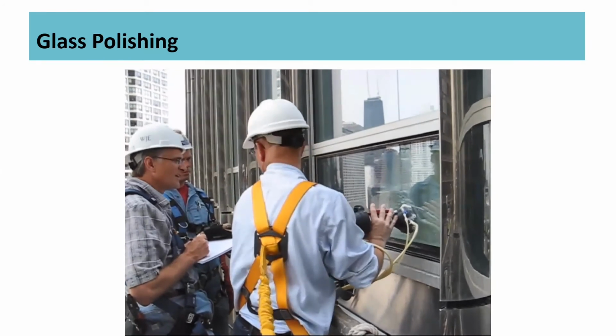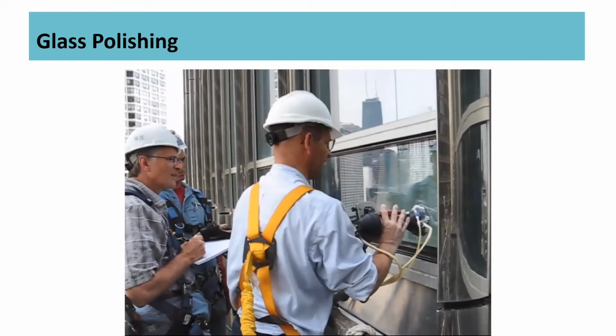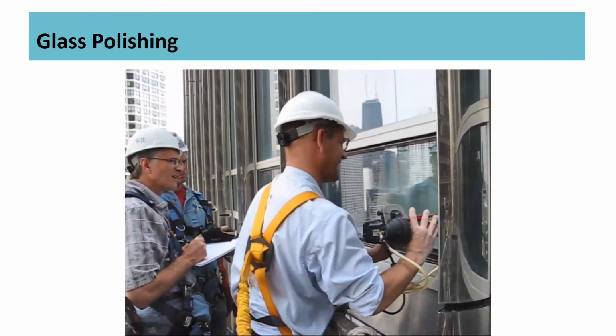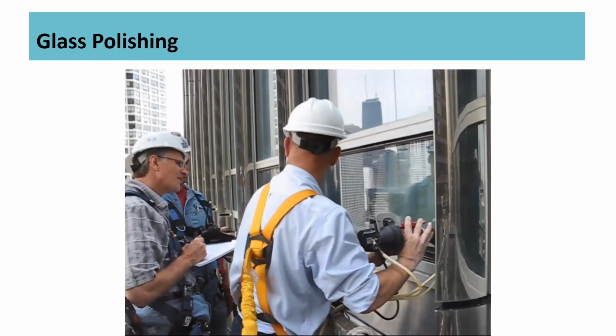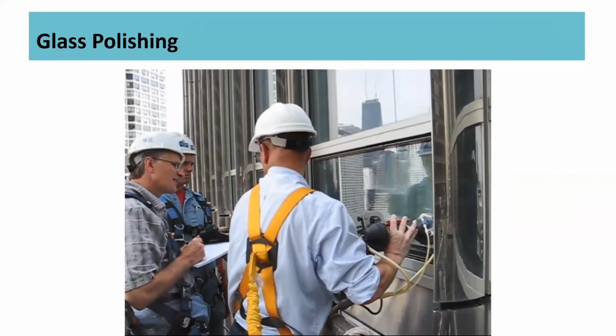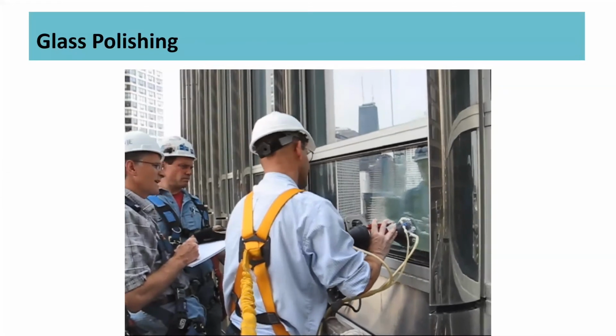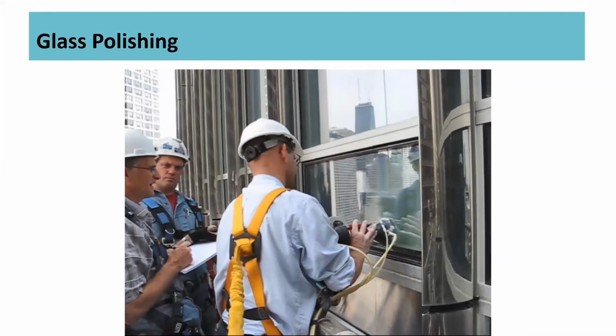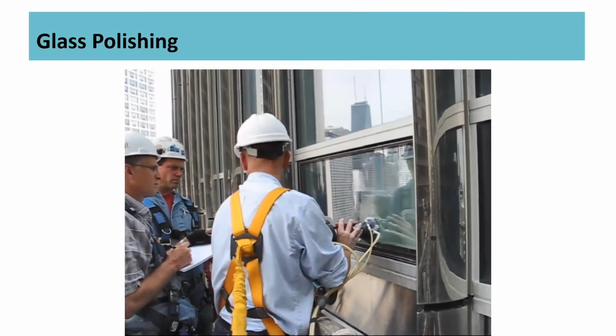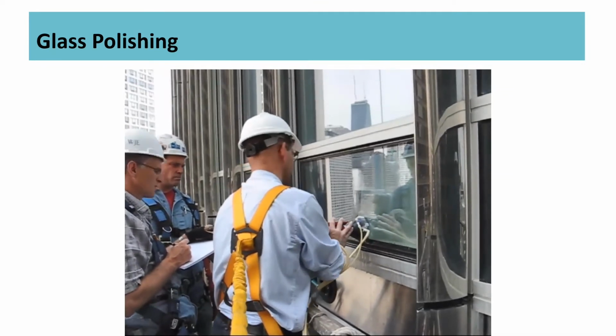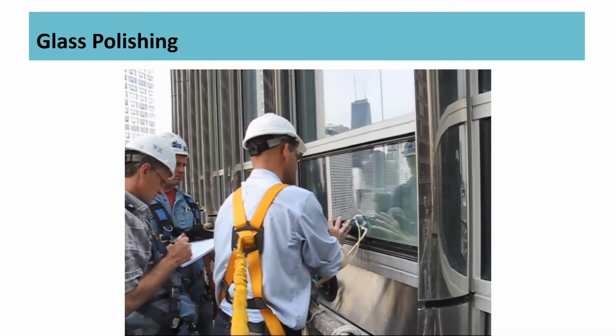However, the equipment is much more finicky. The equipment was developed for use on car windshields, and if precautions are not taken, you'll burn it out. It's not really meant for use for 6 to 8 hours a day on the side of a building. So that has to be accommodated. But it's a much cleaner process.